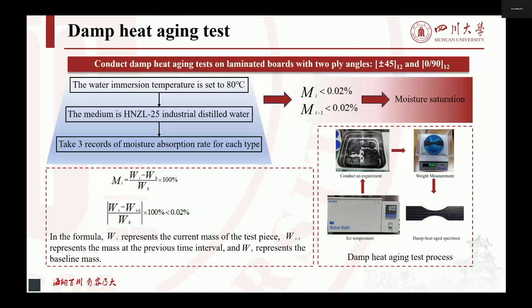To simulate the hygrothermal aging scenario, this project conducted a hygrothermal aging test. The test was conducted in a water bath environment at 80 degrees Celsius, and the test pieces were weighed at corresponding intervals. When the moisture absorption rate was less than 0.02%, it was considered to have reached moisture absorption saturation.